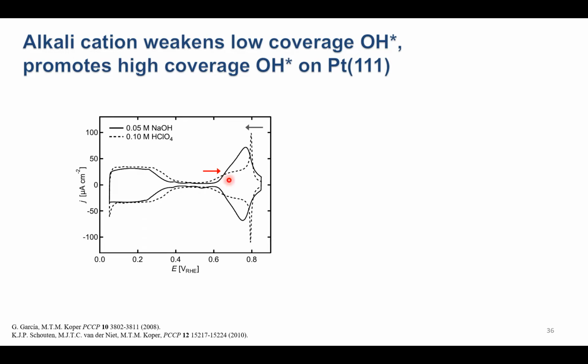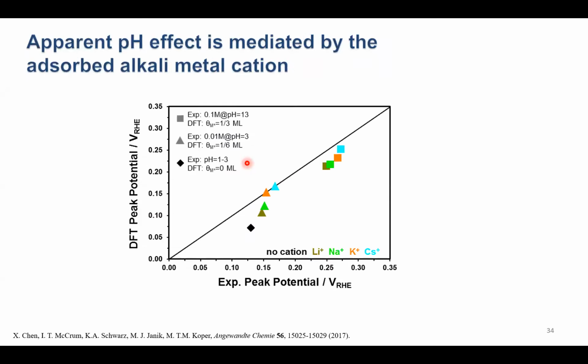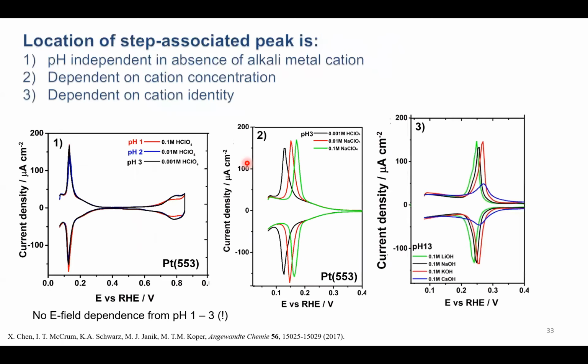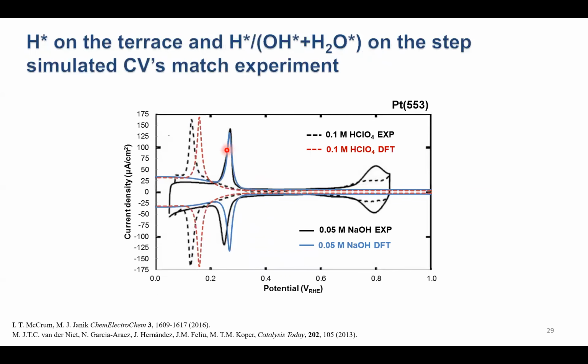But we can see when we increase pH, what we're doing here is weakening low coverage OH adsorption and strengthening higher coverage OH adsorption. This is exactly the same phenomenon that we saw in terms of the effects of pH on the step-associated peak. I didn't mention it, but we actually also see a slightly higher coverage of hydroxide adsorbed in an alkaline electrolyte.